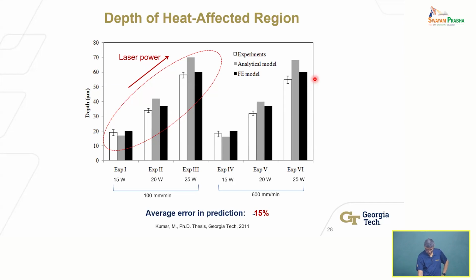All right. Error in prediction is pretty good, 15%. That's actually, in my books, pretty good. Even with the analytical model, you can see it tends to over predict at higher laser powers, because I'm probably not modeling the boundary conditions, and the assumption of plane stress starts getting a little iffy under those conditions at higher laser powers. You see that. But nevertheless, 15% is not bad at all.